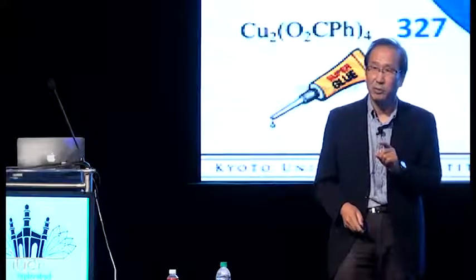At the beginning of my talk, I showed you that in order to prepare a very robust framework, we have to have an energy larger than 200 kJ per mole. But for the recognition, or for the capture of gas molecules, the energy is only 20 kJ per mole. That's enough. This is very important. For capture with low energy, that means we can release with low energy. That's very important. To make a long story short, I just want to show what's happening in this case. In a small channel, 3 CO coordinate to 3 copper atoms. This induces gate opening in the neighbor. So this is a sort of self-accelerating adsorption, reminiscent of hemoglobin. Like this.